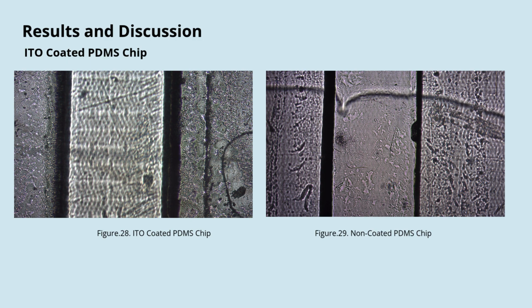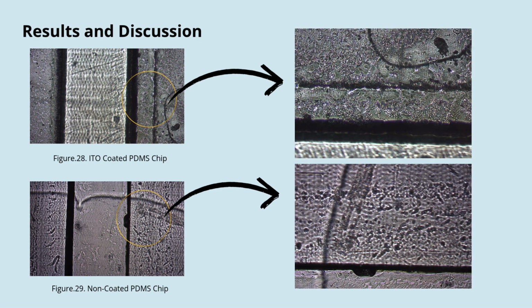Under the inverted microscope images, if we take a closer look between an ITO coated PDMS chip and a non-coated PDMS chip, it can be seen that there are rough textures on the surface of the PDMS cast. While the ITO layer coated the valleys on the surface, it wasn't enough to cover the entirety of the chip, which resulted in uneven layering, causing non-conductive coating.